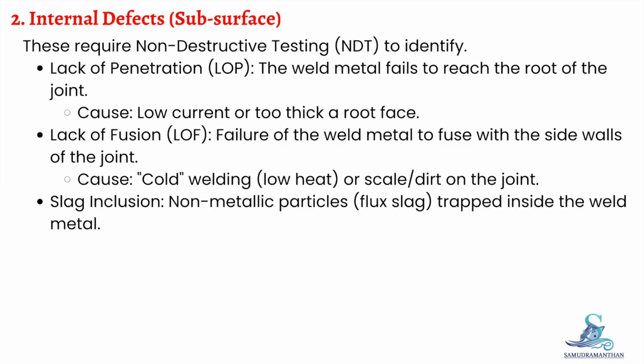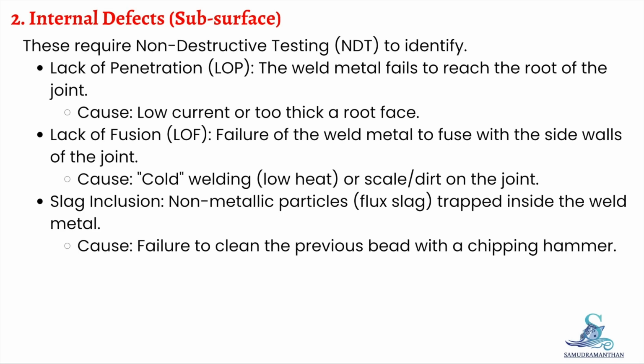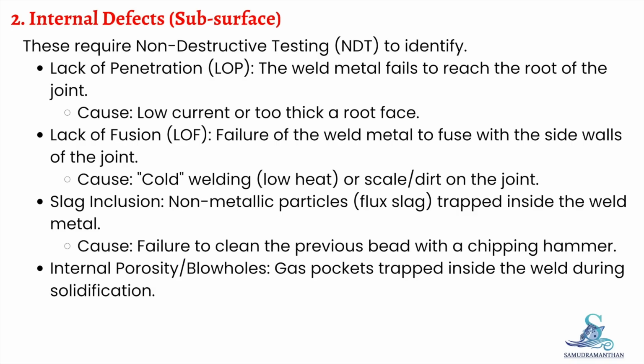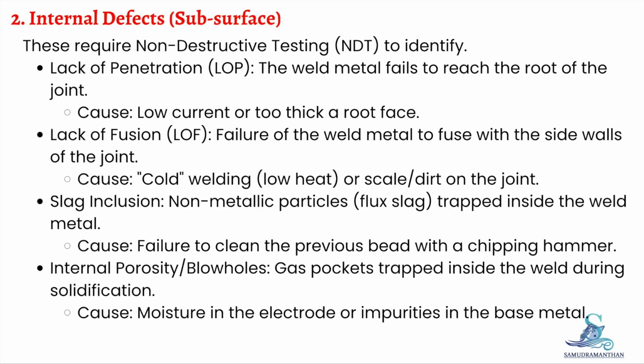Slag inclusion, non-metallic particles, flux slag, trapped inside the weld metal. Causes: failure to clean the previous bead with a chipping hammer. Internal porosity or blowholes, gas pockets trapped inside the weld during solidification. Causes: moisture in the electrode or impurities in the base metal.